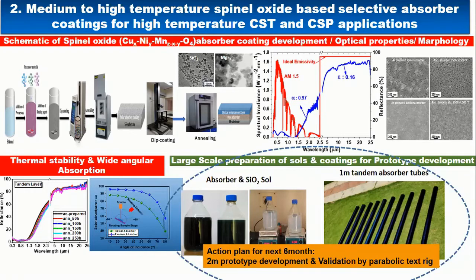Recently, here you can see the thermal stability of this coating. In most parabolic plants, the maximum operating temperature is around 400 degrees centigrade. For that reason, we tested this coating at 500 degrees centigrade for a long duration of 250 hours, and you can see that there is no loss in optical properties. That is a great advantage of this coating. It can be operated in open atmospheric condition.